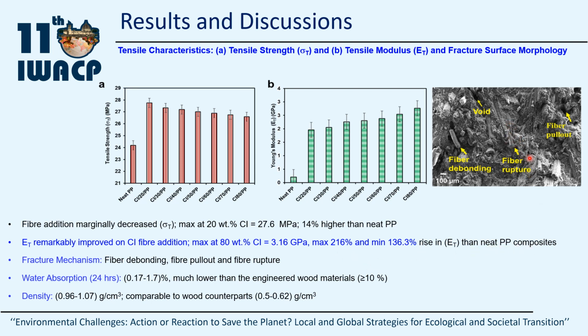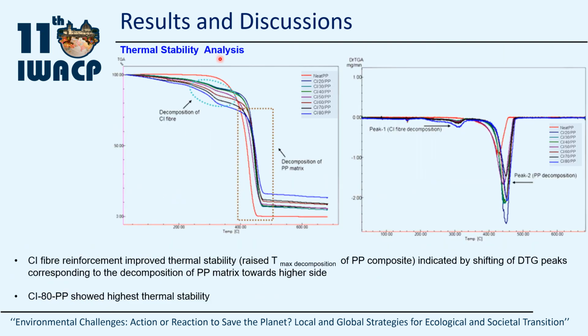The fracture surface morphology revealed fiber pull-out, fiber debonding, and fiber rupture as the major failure mechanisms for the test specimens. In terms of water absorption for 24 hours, the developed composite exhibited a much lower value than the engineered wood materials, which is quite advantageous for maintaining the structural integrity of the developed CIPP composites. The density was found to be comparable to the wood counterparts, and it ranged between 0.96 to 1.07 gram per cc. The thermal stability of the CIPP composite was studied using TG-DTA.